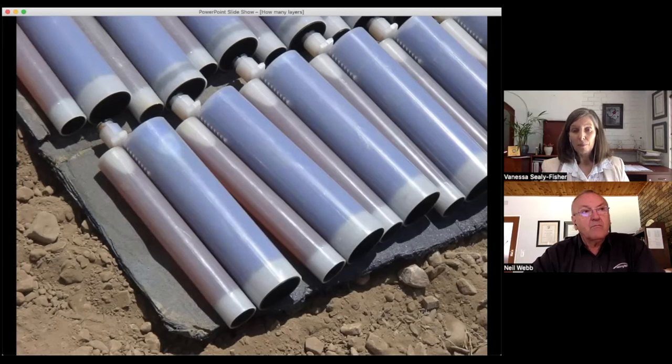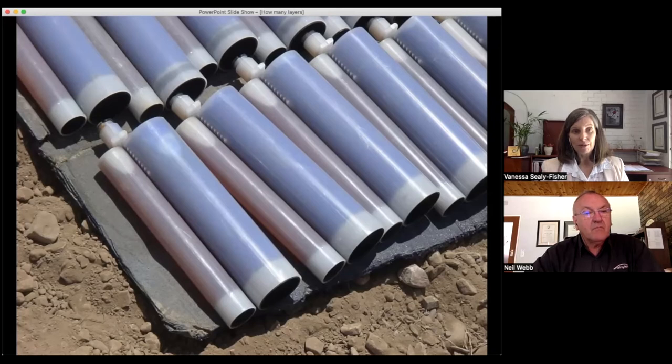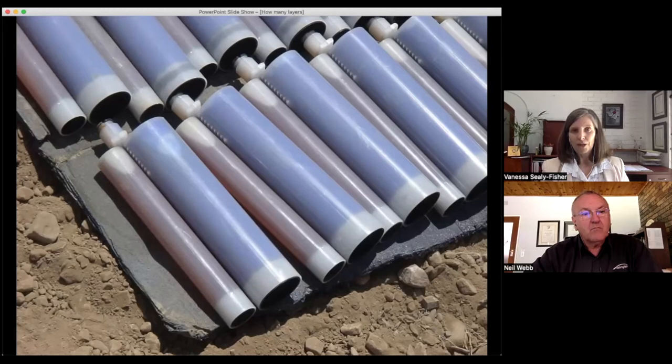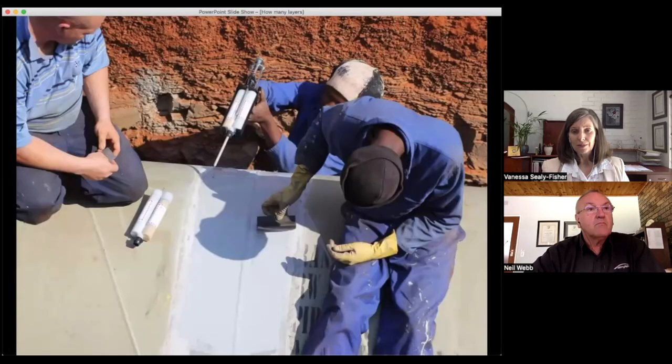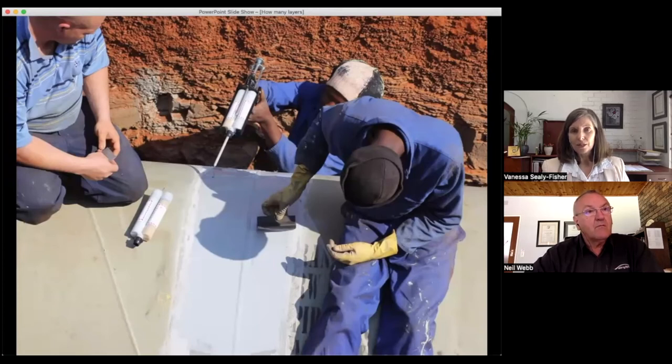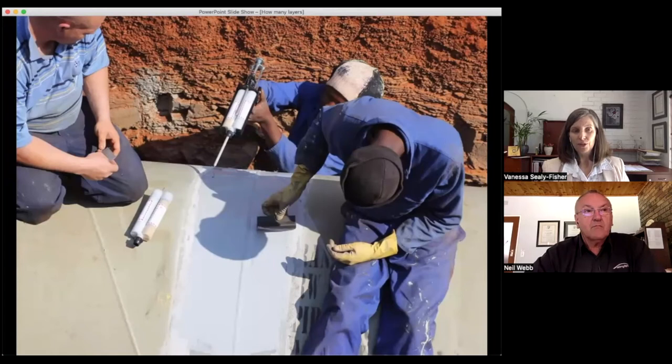In this photograph, we've got a four-to-one ratio of components in this polyurethane, and they need to be mixed in that ratio. Three-to-one or 3.8-to-one is not the same as four-to-one. That really needs to be controlled. Supplying the components for site application makes that easier. They also generate components in different ratios with slightly different properties. You can get one-to-one ratio, as in this picture, for more manual liquid process application.